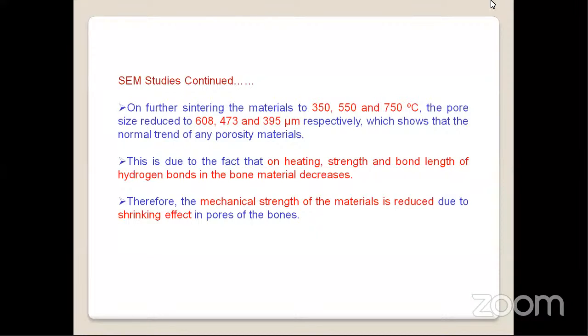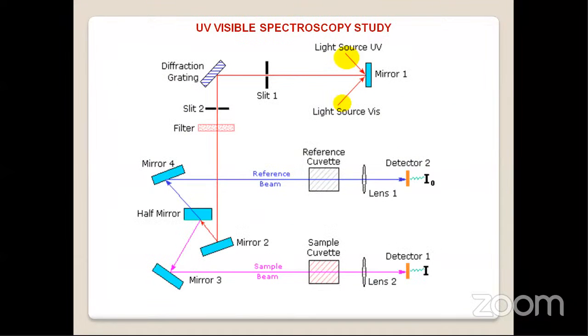For different temperatures, the pore size gets reduced. This is due to the fact that on heating, the strength and the bond length of the hydrogen bonds in the material decrease. The shrinking could be due to the decrease in bond length of hydrogen bonds. Therefore, the mechanical strength of the material is also reduced due to the shrinking effect in the pores of bone. So the bones at higher temperature cannot withstand a maximum amount of load. That's my point. Then UV visible spectroscopy.